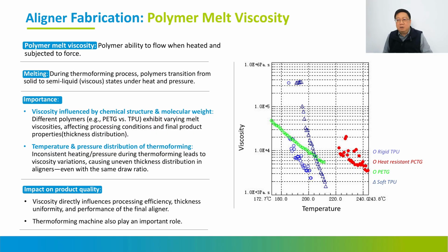Another important point is that currently many thermoforming machines do not have even heating. It means the heat distribution over the whole heating area is not really even. If you use a circular heating system like the BioStar or Ministar, the center area is very easy to overheat, more than 25 degrees higher than the edge area. That means when you put a dental model in to make the liner, the interior part will be much thinner than the outer part. So this is very important. Making a good processing condition, with a good pressure and a good temperature distribution, is very important.